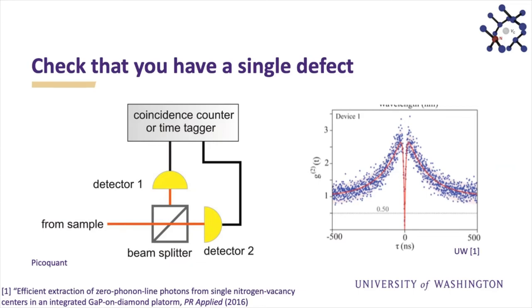And then of course there are two bread and butter measurements that you have to do. One is you have to check that you have a single defect. You see something that's very bright, it's very stable, but you always have to prove that you only have one atom, or two atoms missing in your lattice, that creates this quantum emitter. The way we do that in the lab, we take the photons from that defect, we split them on a beam splitter, and then we do coincidence measurements.